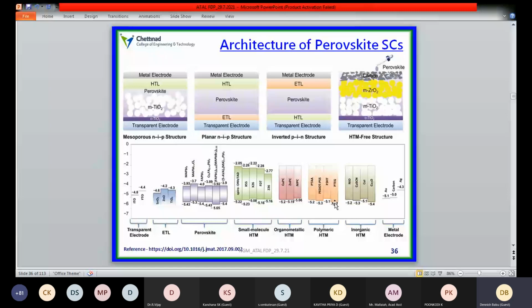From that they can fabricate the solar cells and devices, and they have also exhibited some kind of reasonable power conversion efficiency. So at the bottom of this slide, I have given the various materials and various perovskites used for the application of perovskite solar cells. So traditionally, the transparent electrode is made of indium tin oxide and fluorine-doped tin oxide based systems. And as I mentioned, the electron transporting layer may be tin oxide, zinc oxide, and titanium dioxide based material. The hole transporting layer may use different materials like polymeric, inorganic, organometallic, and small molecule material also used for the hole transporting layer applications.